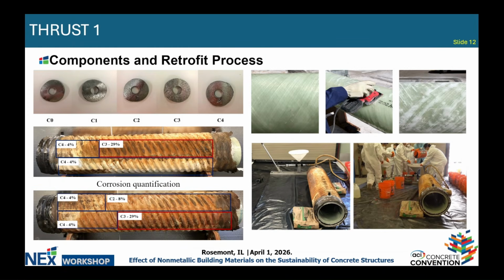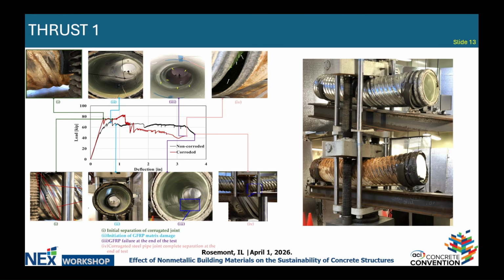Full-scale structural tests were conducted. So under bending, these full-length pipes were investigated and load deflections were observed. There was an initial separation of the corrugated joint. Then we had GFRP matrix damage. Then we saw some GFRP failure as well. Now, these are tested to failure. So you're looking at an overall response here. Then you also see some of this seam joint, lock seam joint separation, the corrugated steel pipe joint completely separated at the end of the test.